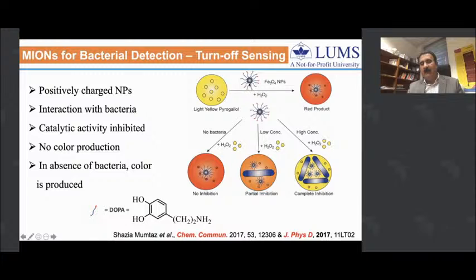But if you control the chemistry of these iron oxide nanoparticles by coating with dopamine, for example, in this case, so that they become positively charged and interact strongly with bacteria. So in the presence of bacteria, iron oxide nanoparticles will be coated by these bacteria, and then they will not be able to convert this yellow substrate into red product. So we designed these iron oxide nanoparticles, highly stable, and then controlled their surface chemistry by coating these dopamine ligands to figure out how useful they can be to detect bacteria in drinking water. In this way, we were able to detect bacteria in drinking water, but unfortunately, their sensitivity is not that great that they can be commercially employed for this purpose.